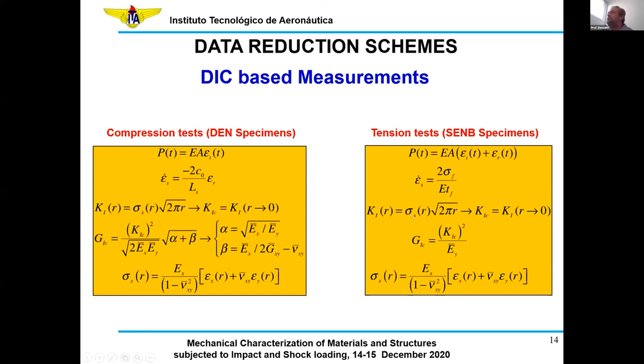We can measure the strain field ahead of the crack tip. And by using Westergaard, we can compute the stress intensity factor. And by extrapolating that at the crack tip, we have the KIC at the moment of failure determined at different strain rates. As for the damaged configurations, we have plane strain conditions, so we can convert the stress intensity factor into fracture toughness by using this expression here, where E bar is the effective laminate Young modulus.